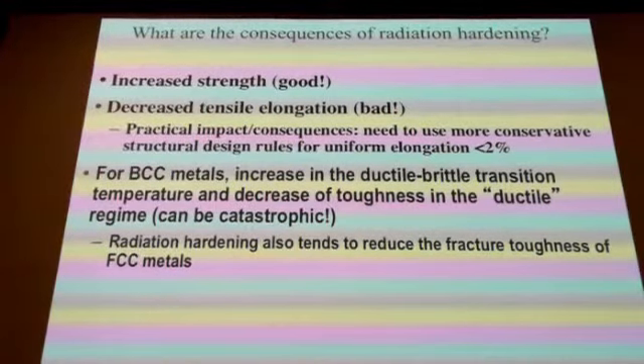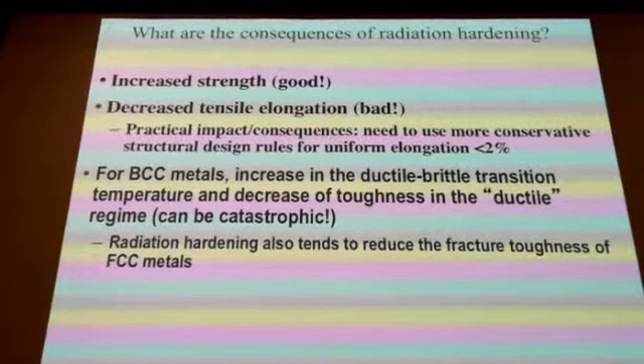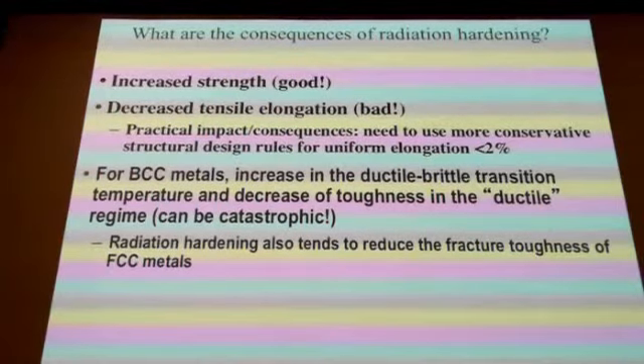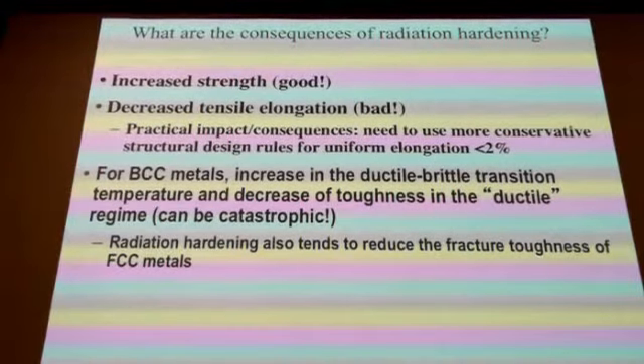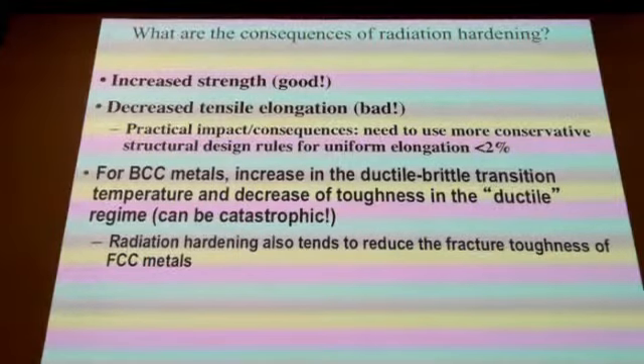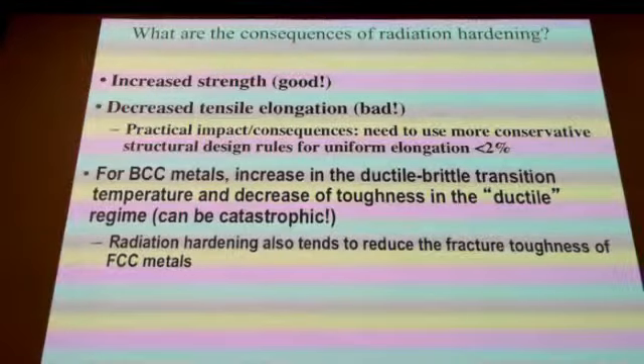But of course, along with that increase in strength, there are negatives. In particular, in essentially all cases, you get a decrease in the tensile elongation of the material that might cause you to have to adopt more conservative structural design criteria rules for the structural material, particularly if the uniform elongation goes less than 2%. And for BCC, body center cubic types of metals, you can also have an increase in the ductile to brittle transition temperature and a decrease in the upper shelf toughness, which could be a catastrophic kind of an event to be avoided.